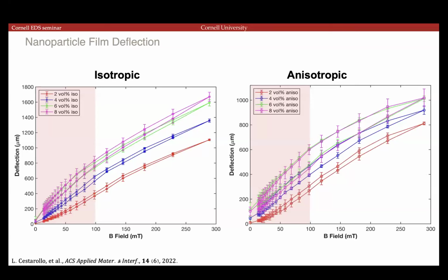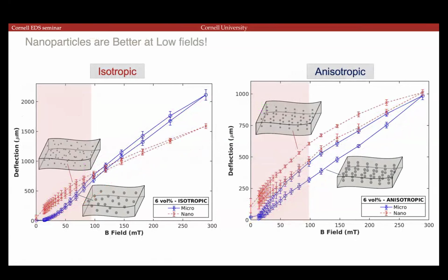Microparticles, because of their larger mass, are going to have a lot more inertia. So it's quite likely that these nanoparticles are able to deform more than the microparticles. If we compare just the same volume concentration of each directly, then you can see that. The microparticles are the ones in blue, and the nanoparticles are in red. If we apply a really small magnetic field, the nanoparticle films immediately start to deflect, and we even get 3/4 of a millimeter deflection in just the 100 millitesla field range. And then for the anisotropic films, their deflection is larger than the microparticle films at all fields.